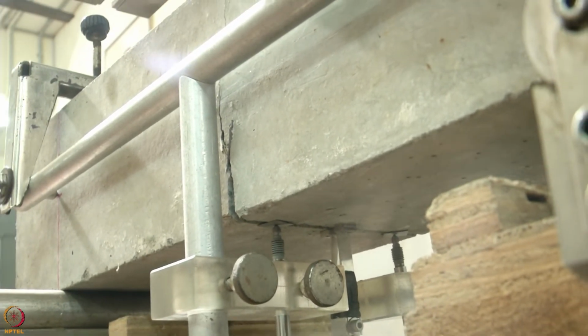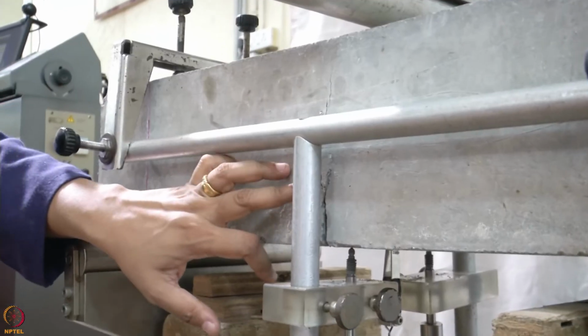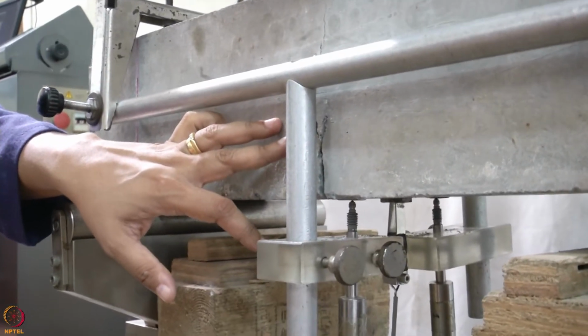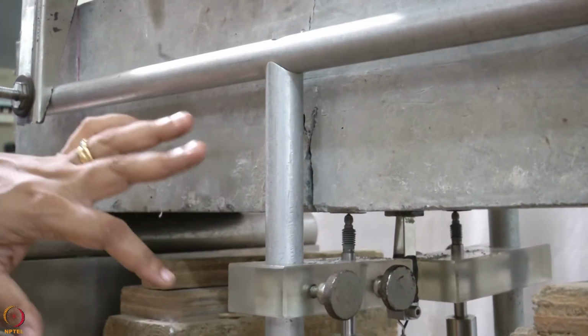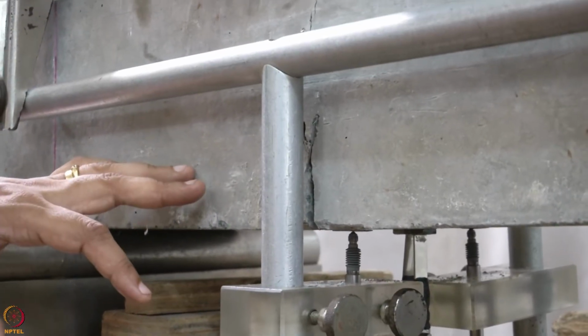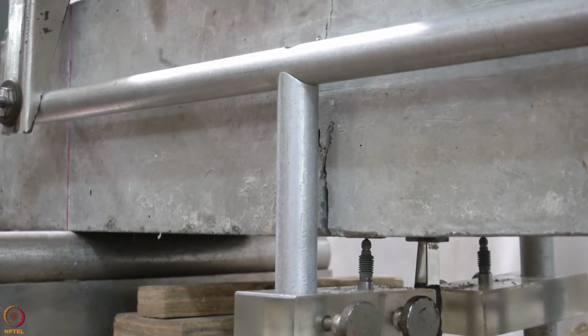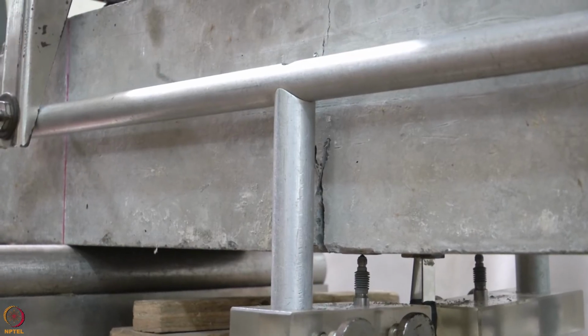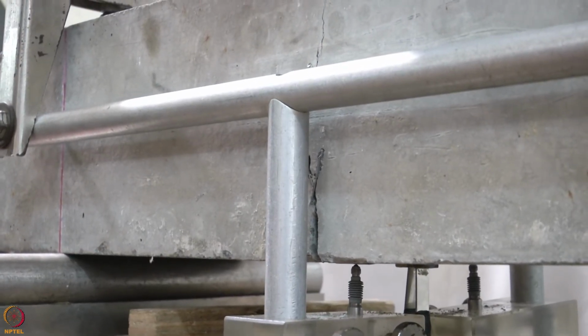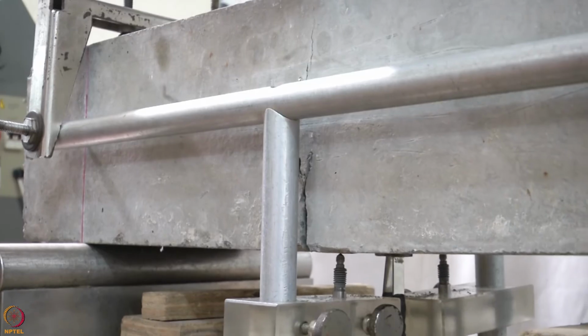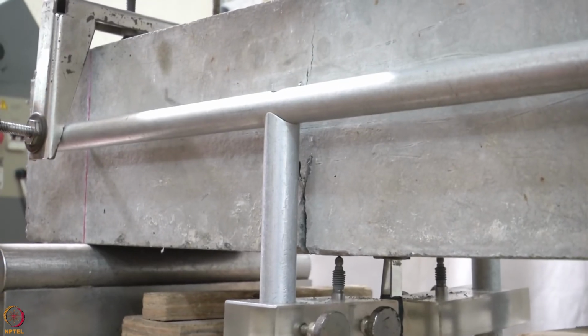Now the test is completed. As you can see, although a crack has developed, there was no brittle or catastrophic failure. That's because of the presence of fibers in the concrete. At the same time, we have got the post-peak response, that is the performance of fibers after peak. So the load carrying capacity at different crack openings can be derived from this test. Now our test is complete.